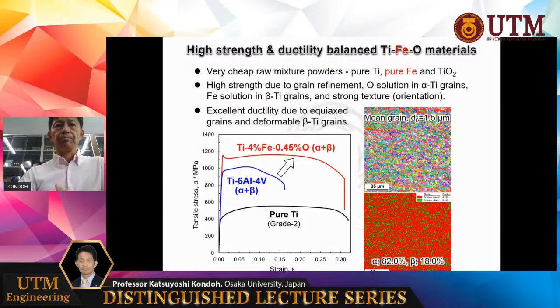They showed very high strengths and very good strain ductilities compared to titanium 6-4, 6 aluminum, 4 vanadium alloys. This is a very famous titanium alloy used for aircraft. As compared to both, our developed materials showed much higher strengths and ductilities. That means a very good balance between high strength and high ductility. So that has very high reliability for use in construction materials for aircraft or passenger cars.